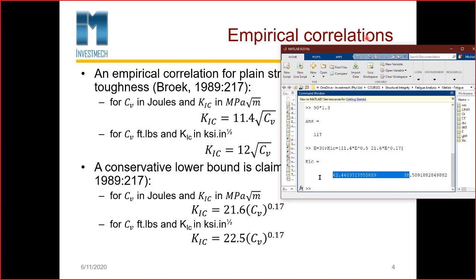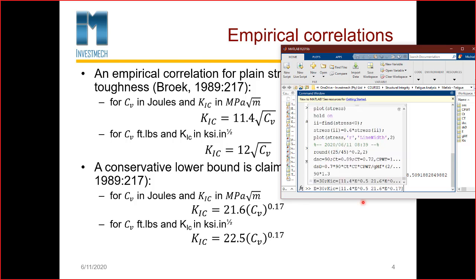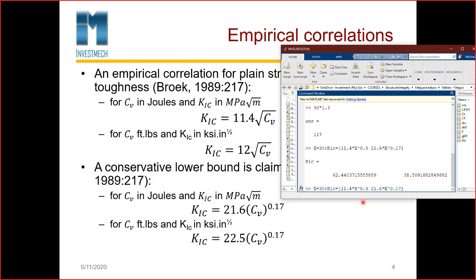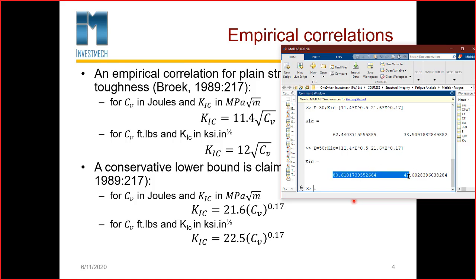You will realize that many steels are in that typical range. If you have a large energy value, say you measured something like 50 joules, then we end up with 80 and 42 MPa square root meter. The 42 is the lower bound — a very conservative lower bound — but we do use that to design. We like that conservatism when estimating the maximum allowable or the critical crack size on a cross section.